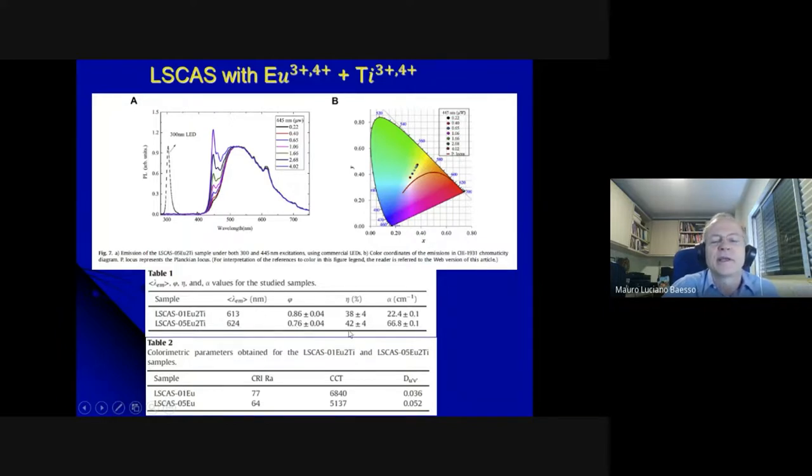you see here the fluorescence, because one aspect I didn't mention yet: all these samples, we measured the quantum efficiency using the thermal lens technique, the thermal mirror technique, as I said in the beginning, we have in our lab. So we have a technique to study the fluorescence quantum efficiency, because it is one important parameter. How much energy you are going to put out. You illuminate your sample with an LED. How much of the light from the LED will be converted to light emitted from the phosphor.